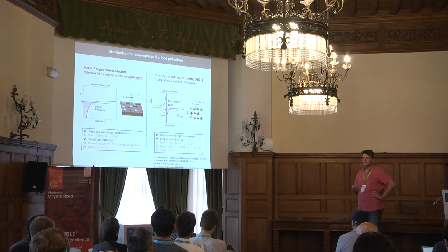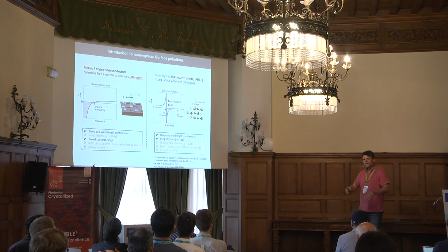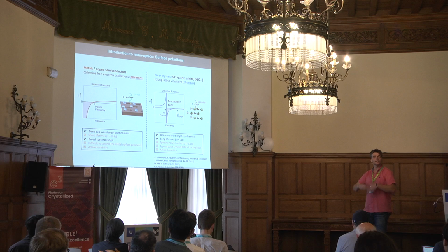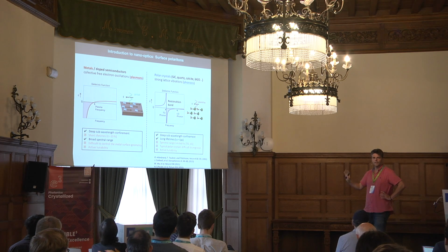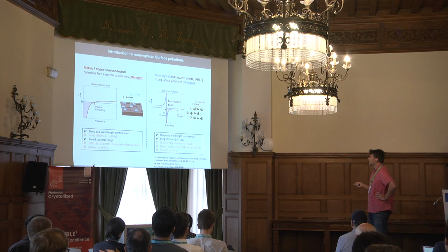On the other hand, as it involves phonons, scattering occurs in time scales much longer than electron-electron scattering. Therefore, long lifetimes, in the picosecond range. Therefore, you can make nano-optics; you have more time to do it. And if you make cavities, they can go back and forth in the cavity many more times, and then the quality factor can be larger, and you can make, for example, nanocavities that are much better for sensing. But everything occurs in the infrared: 10 microns, 7 microns, 11 microns, 12 microns.